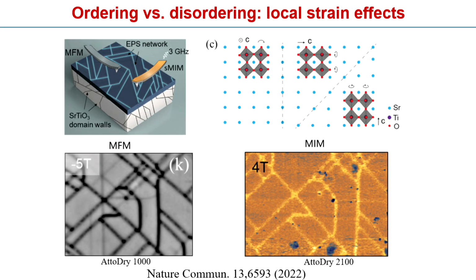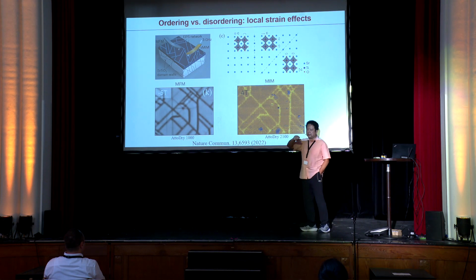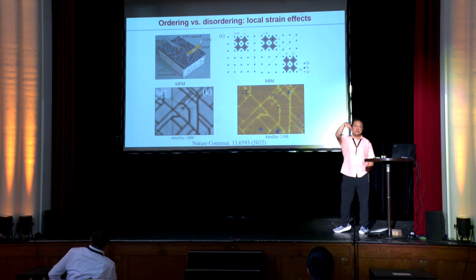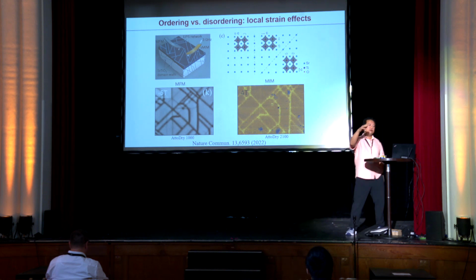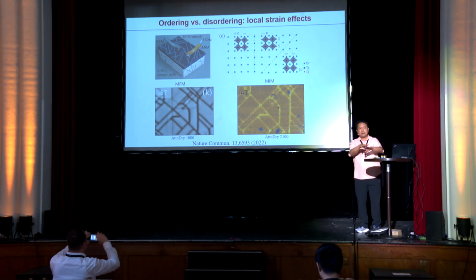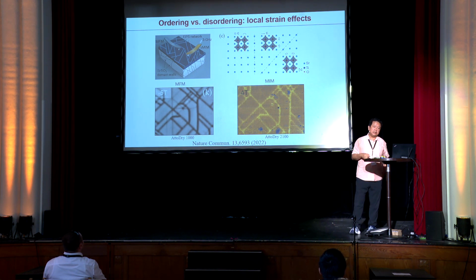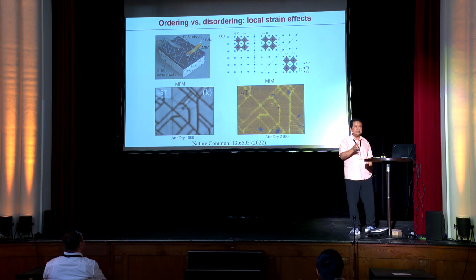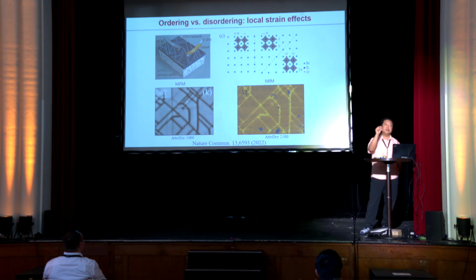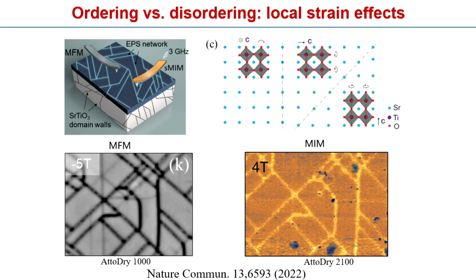In fact, you don't even have to use chemical interdiffusion to introduce disordering. You can just make some local lattice distortion that also introduces disordering, which will also lead to electronic phase separation. Again, this is the perfectly chemically ordered LPCMO system grown on an STO substrate. But through the cycle of temperatures, there's going to be a structural phase transition of the substrate from cubic to tetragonal phase. When it's in the tetragonal phase, there are tetragonal structural domain walls. That domain wall will go away when you raise the temperature to room temperature. However, when the domain wall is present, it introduces some local lattice distortion in these superlattices. And the local lattice distortion immediately leads to electronic phase separation, where we can get these magnetic images and also conductive images of the same surface location.